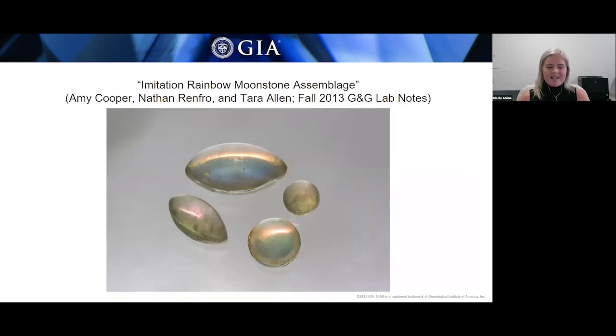Another interesting imitation that was seen at the Carlsbad Laboratory were these semi-transparent to translucent cabochons. They had a white body color, and they ranged in size from about 1.5 to 10.5 carats. From their appearance, again, someone might assume that this might be rainbow moonstone. But with microscopic examination, these proved to actually be assembled material composed of a colorless transparent base cemented to a white top and then coated in a colorless plastic.